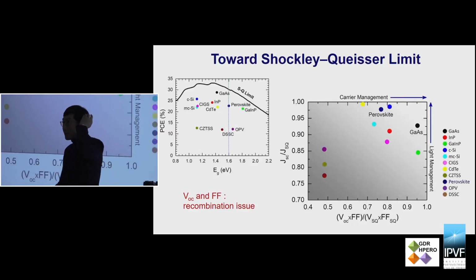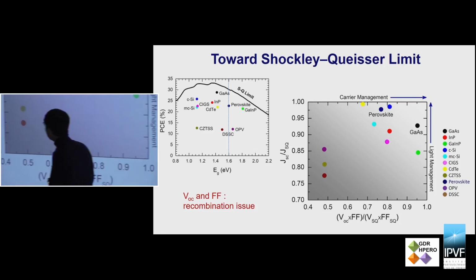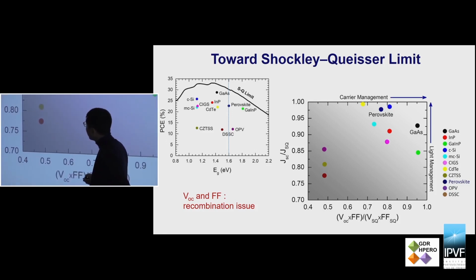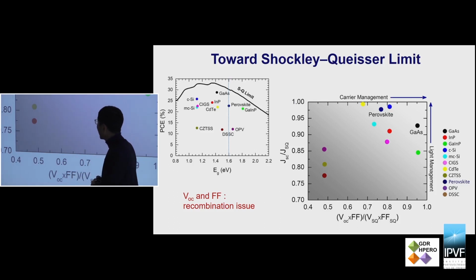For higher efficiency, this is the well-known Shockley-Queisser limit based upon the band gap energy. For instance, if you use 1.4 eV gallium arsenide, then almost 30% efficiency can be achieved. This is real data, the observed efficiency, and in that case the theoretical efficiency is around 33%. In the perovskite case, if you use 1.6 eV, for instance MAPbI3, then the theoretical efficiency is around 30.5% according to the Shockley-Queisser efficiency calculation.